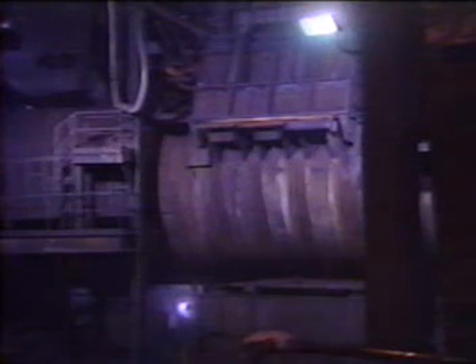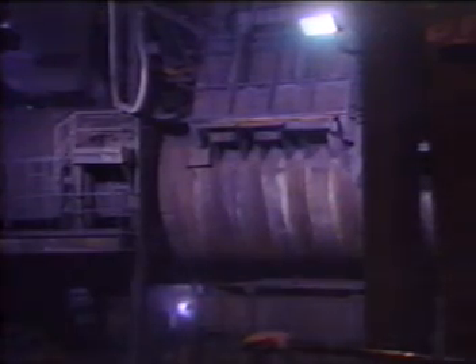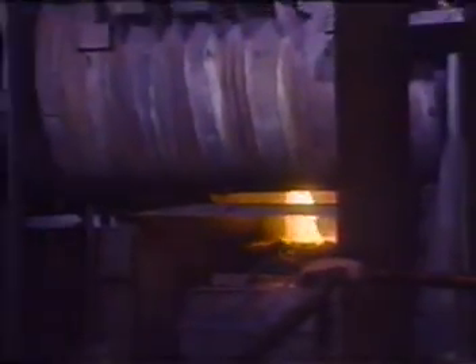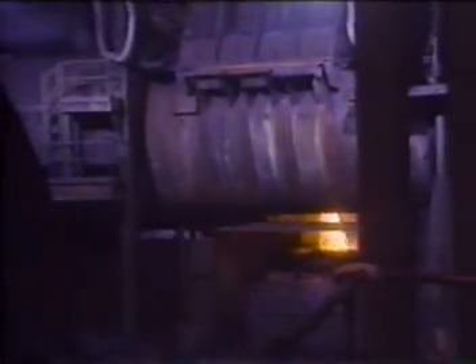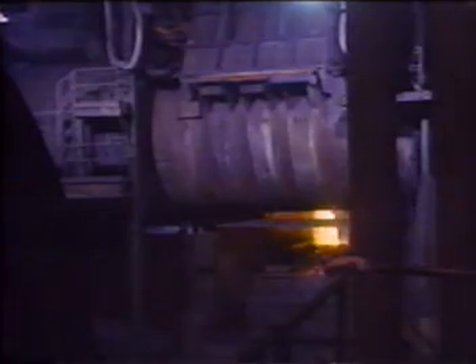Copper concentrate was blended with flux, coal, slag mill concentrate, precipitate copper, and other materials. This mixture was fed into Noranda reactor furnaces that contained a molten bath of iron slag and copper matte. Oxygen-enriched air was blown into the bath to oxidize the sulfur and iron, creating sulfur dioxide and providing a turbulence to help smelt and digest the new feed.